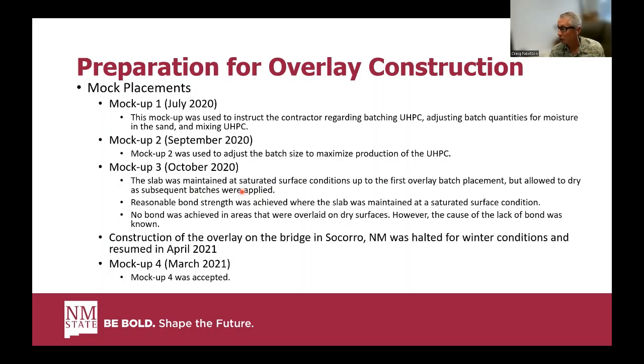The problem was that after they batched the first batch of UHPC, they then allowed the substrate to dry. So everything looked good where the substrate was wet for that first batch. But after that, on a dry substrate, they didn't get bond. However, NMDOT accepted the mock placement. Even though there was no bond, we understood the reason why. The contractor understood the reason why. So we were thinking that we were ready to go to construction.